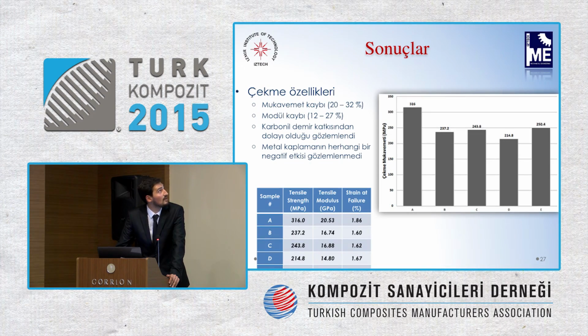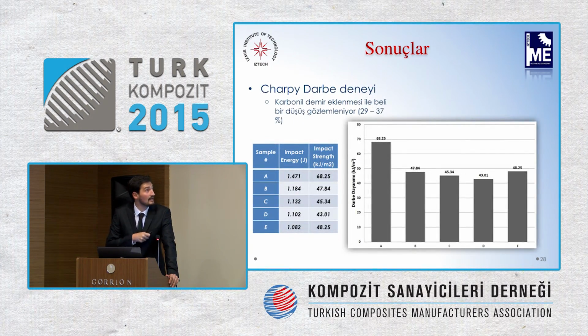Tensile properties on tensile strength and on modulus, there are losses around 20%. Our reference sample is shown as A, but on the other samples there are losses. Maybe we can think that the variation might be similar, but the difference is an observable one, a big one. Carbonyl iron was added here. This might be the reason, because as the number of resistive layers increases, there is no decrease, but when carbonyl iron is added, there is a decrease. So this is not only true for tensile, but in the impact test there is a 30% loss together with the addition of the carbonyl iron.